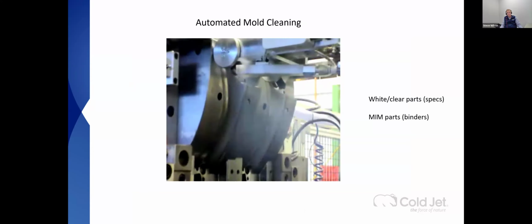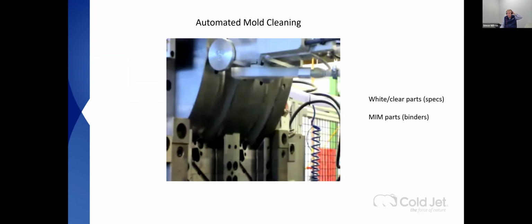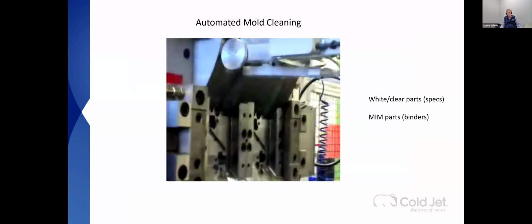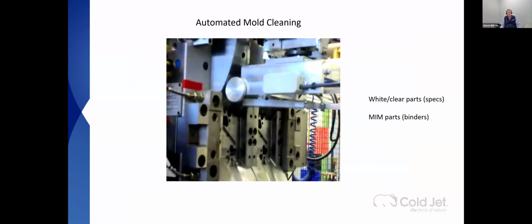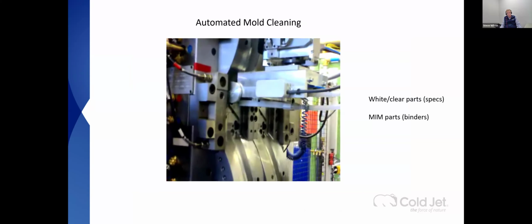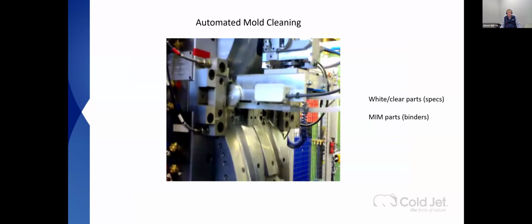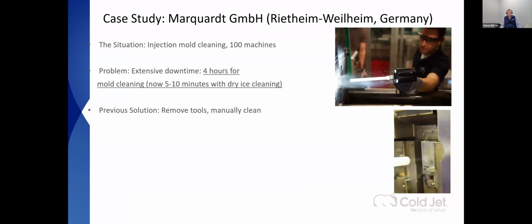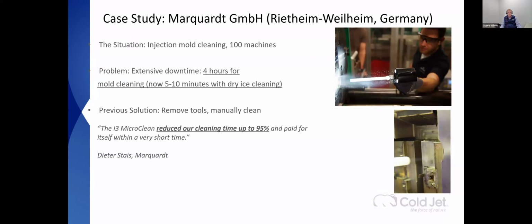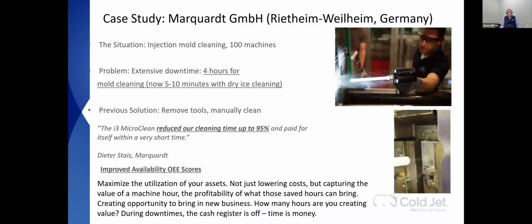Sometimes if you're running a white part or a clear part, or you're running a metal injection molded part, you might have a binder that's causing a waxy substance on the mold. You might have to automate the cleaning cycle more frequently than you would cleaning thermoplastics. You can automate this if you have to. Marquardt went from 4 hours down to 5 to 10 minutes, reduced their cleaning time 95%. That's an improved availability OEE score, maximize their assets. So time is money. All right, this is Marquardt. It went faster.